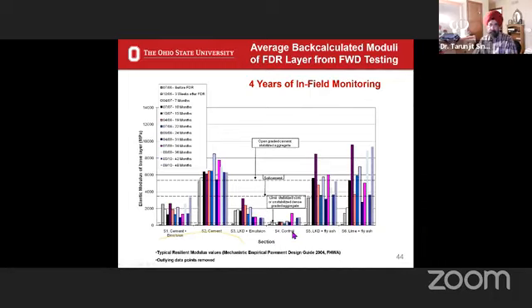Simply means that we took the material, we pulverized it, added water and compacted, right? So you can see there is some improvement, not significant. It was clear to us that the emulsion that we used did not really benefit along with the cement. You can see cement is here. Look at cement and emulsion. I would have expected better results.